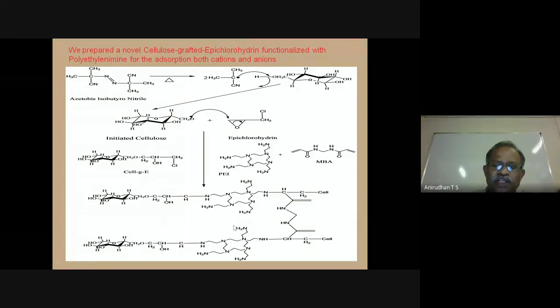And what is the advantage of this amino group? This material can be directly utilized to capture metal ions, because we have a donor nitrogen atom which coordinates with the metal ions. Even otherwise, you can treat it with succinic anhydride. Your NH2 becomes NH-CO-COOH, something like that. We can introduce a COOH group, a sulfonyl group, and even treated with HCl, we have quaternary salts.